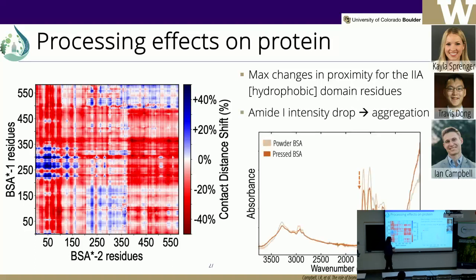Then if we take the FTIR of this, with the powder over here and the pressed material over here, you see a very characteristic reduction, and this is normalized to one of the peaks. I should know which peak it is normalized to. Nevertheless, you do see a reduction in your amide 1 peak, and that in conjunction with the residue proximity maps,